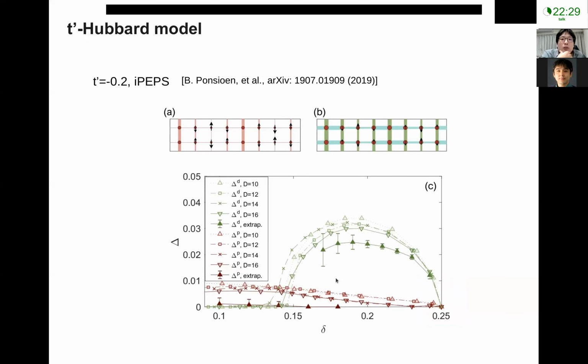This T-prime Hubbard model was also studied by iPEPS, and for negative T-prime equal to 0.2, they found there's actually a finite superconducting state in the doping range from 0.15 to 0.25. They also found coexistence with the stripe order, although it's a bit weaker, and the pairing symmetry is D-wave.